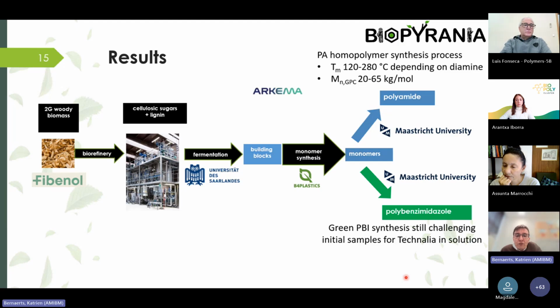At Maastricht University, we use those monomers to make polyamides and polybenzimidazoles. And for the polyamides, we made already homopolymers. We developed the process. Depending on the choice of the diamine, we can tune the melting point between 120 and 280 degrees. And our molecular weight is, depending on the choice of the comonomers, 20 to 65 kilogram per mole